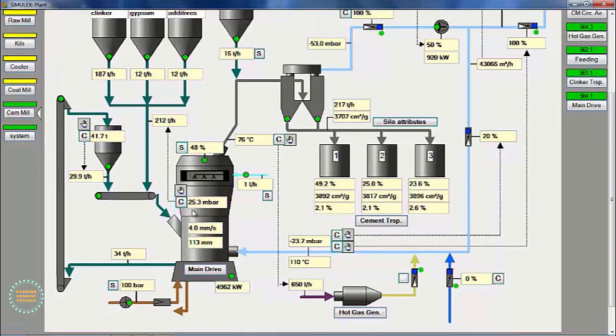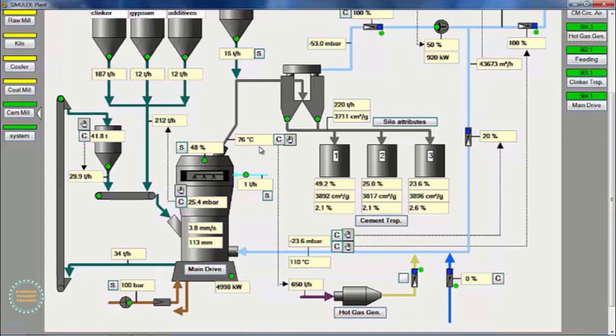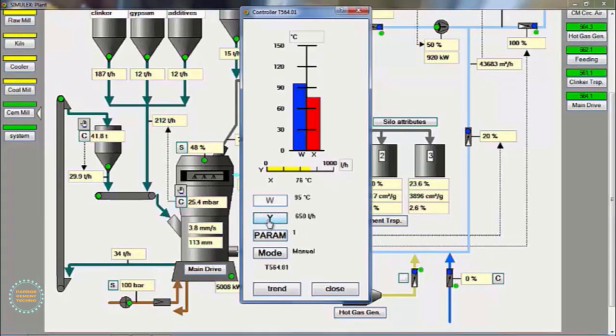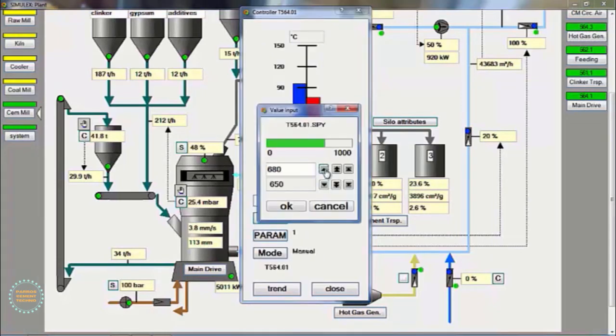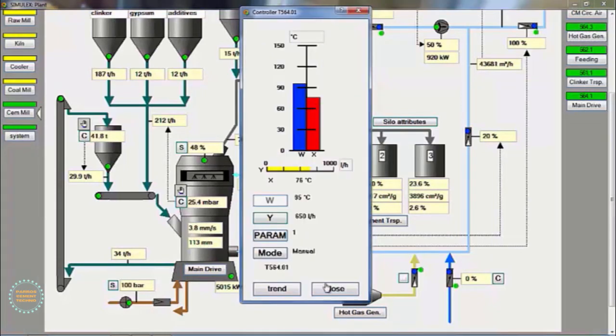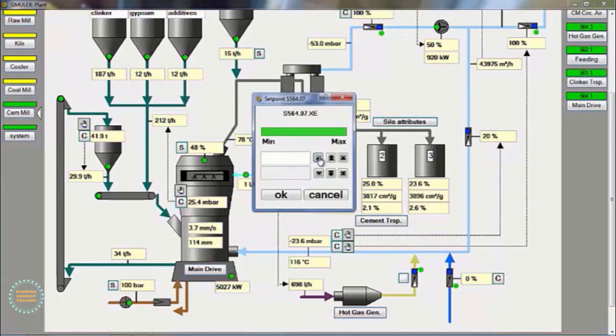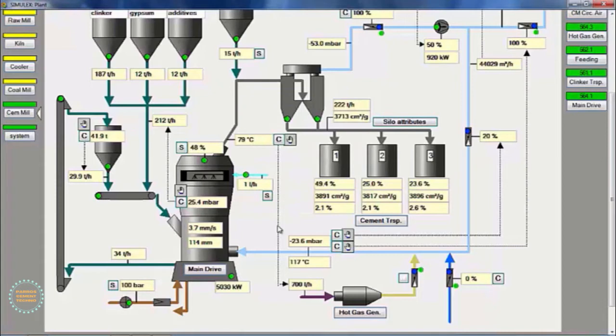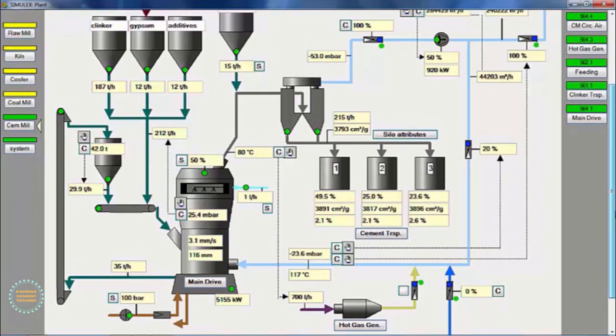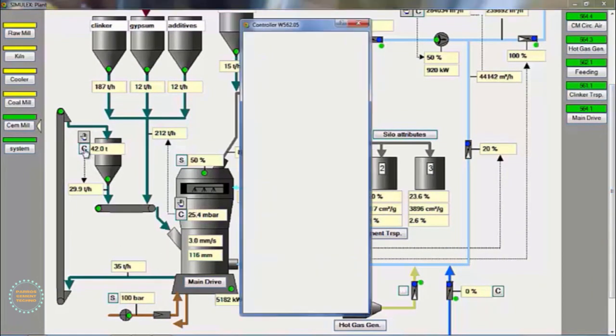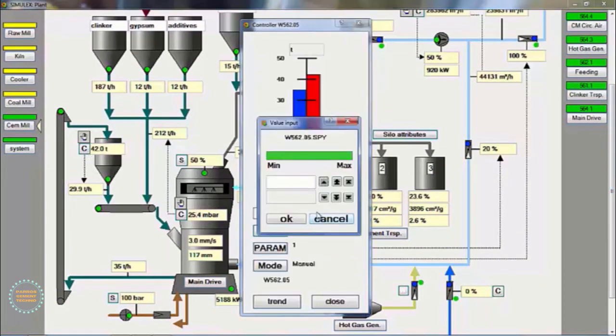We will now optimize the operation of the VRM cement mill. Before adding feeding, it must be noted that the outlet mill temperature is maintained between 75 to 85 degrees Celsius. If it is less than that, it can increase fuel consumption. We must always observe the bed material and mill vibration before and after increasing the feeding. If the bed material tends to rise, hydraulic pressure can be added.